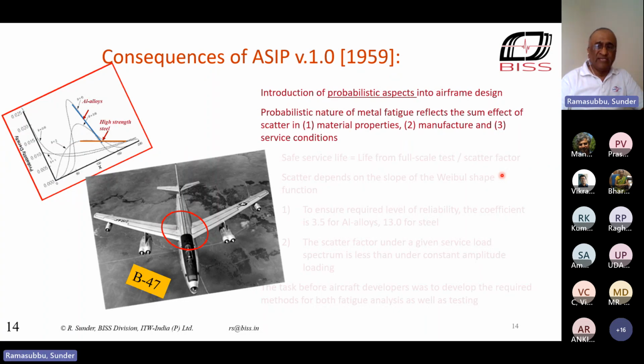So it turns out that, as I've shown over here, if you look at the Weibull distribution for probability of failure of different materials, aluminum alloys will have much less scatter in fatigue life than high strength steel. So immediately it turned out that, if you're testing a steel structure, you have to use a different scatter factor by which you have to divide the fatigue life that you obtain in order to tell someone that he can use the structure for a certain period of time, whereas that factor would be less if it was aluminum alloy. So the material itself has a huge contribution to what kind of scatter it will be.